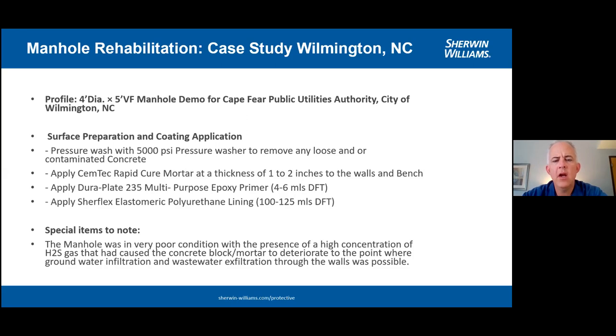The manhole was in very poor condition because of the high presence of hydrogen sulfide gas that had caused the concrete block and mortar to deteriorate to the point where groundwater infiltration and wastewater exfiltration through the walls was possible. They were actually losing sewage into the ground through this manhole.